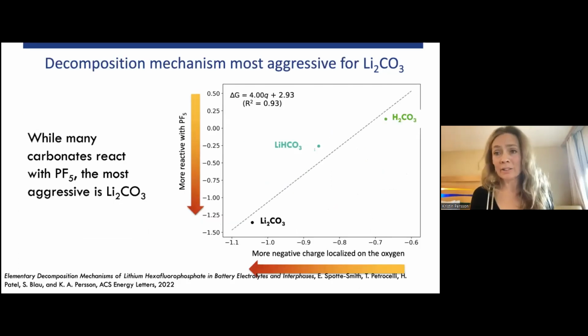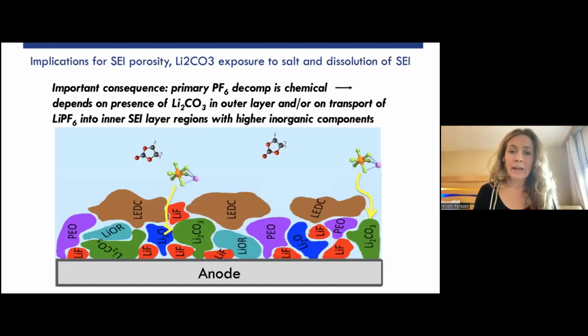We also found that lithium carbonate is not the only one, but it is the worst as far as we can see. It depends on the anionic nature of the oxygen, how badly it decomposes PF5. Other kinds of carbonates also do it, but not quite as vigorously. And it does say something about the importance of the porosity of the SEI and the importance of the Peled model of actually having that organic protective layer, so as not to expose the inorganic species that form close to the electrode to PF6. But in the very beginning, they are exposed, right? So maybe the jury is out on how much lithium carbonate is left once it reacts with lithium PF6 or PF5. Dissolving the SEI is obviously bad too, because you could also expose it to those things. So this may give us a clue on how some of these SEIs don't work in the future.